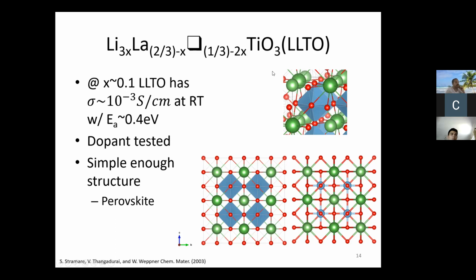Yeah, good question though. What they're basically saying with the fractions is you could think of it as a probability of having a lithium or a lanthanum in that site. So if X equals, say, 1/6, which is the case here, 2 times 1/6 is 1/3, so you have no vacancies. 3 times 1/6 is 1/2. 2/3 minus 1/6 is 1/2 as well. So half of these A sites are lithium and half of them are lanthanum. Does that answer your question more or less?